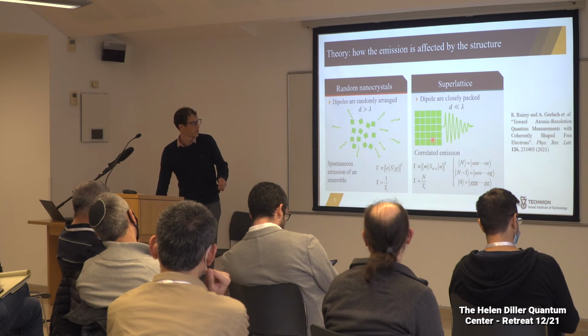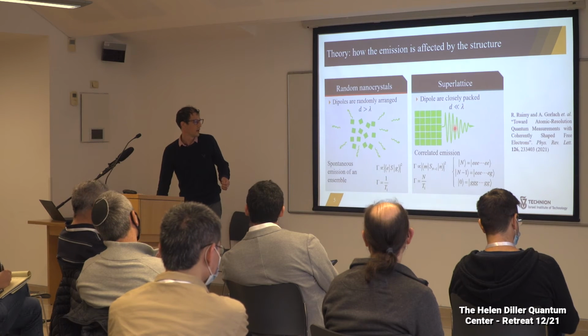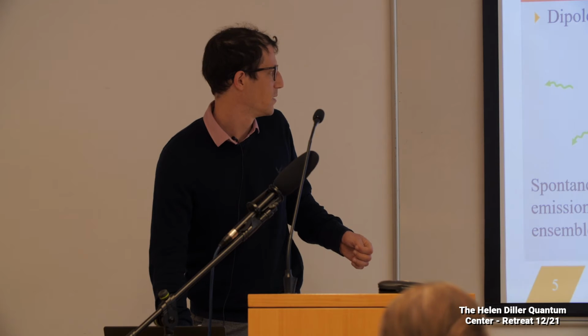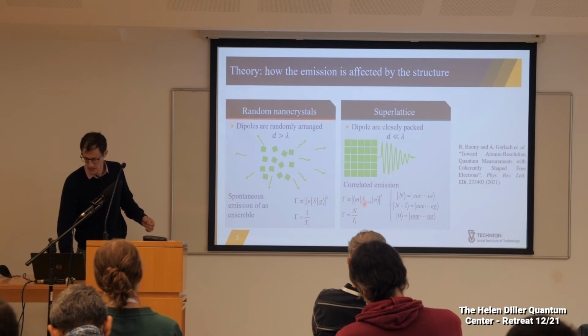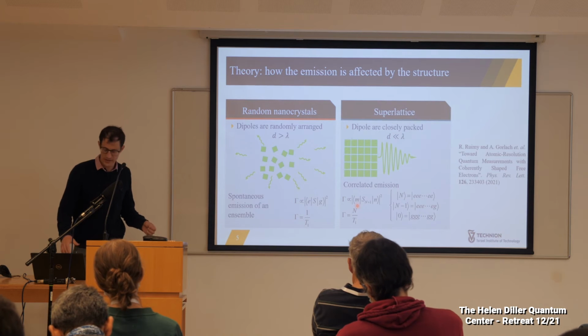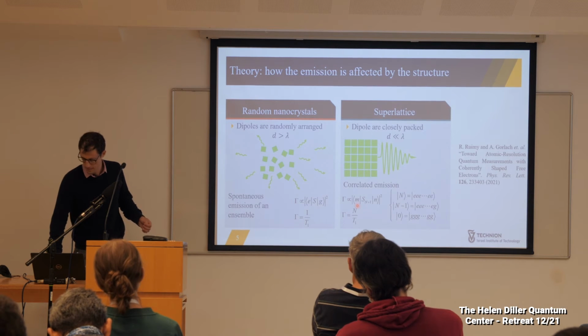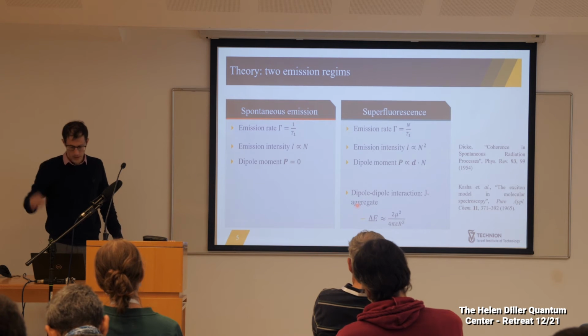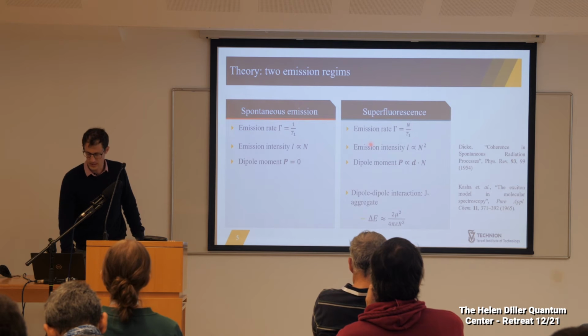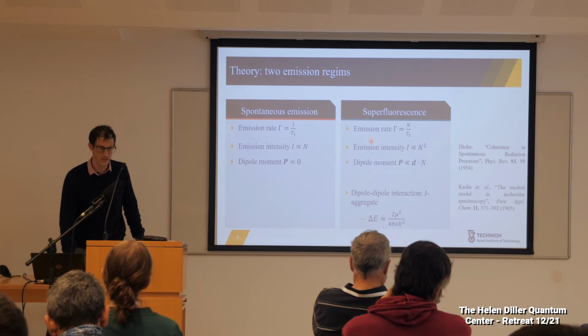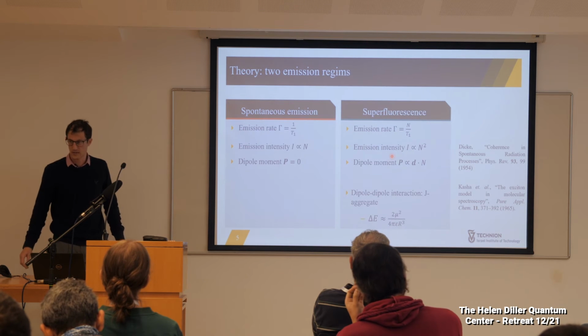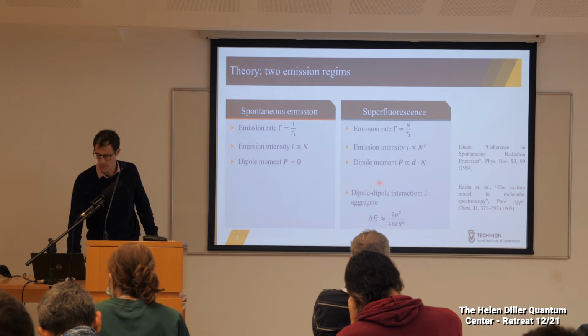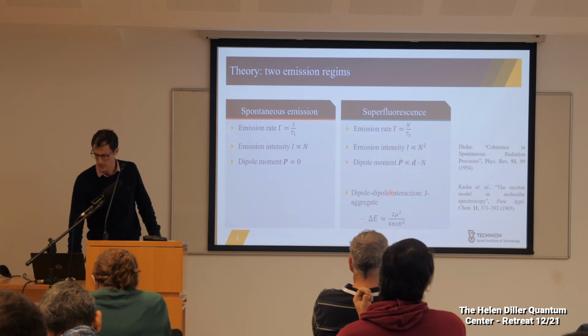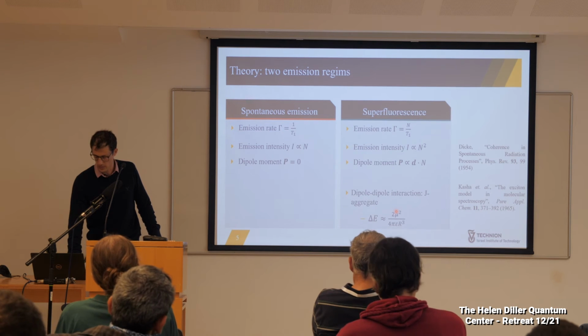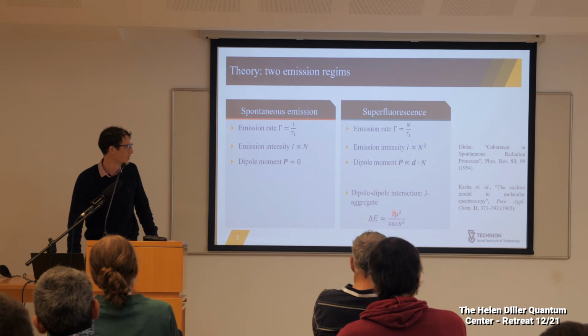Now, if you take these quantum dots and put them together into a small region, the states become multiple quantum dot states, and the transition matrix changes accordingly. The surprising result is that the emission rate increases by a factor of the number of quantum dots that participate in the emission. So experimentally, we expect to see an emission rate increase by a factor of n, and the same for the intensity. We also expect to see a non-zero dipole moment, and another mechanism that causes coupling is the dipole-dipole interaction, which shifts the emission energy proportionally to the dipole moment squared over the distance between two emitters cubed.